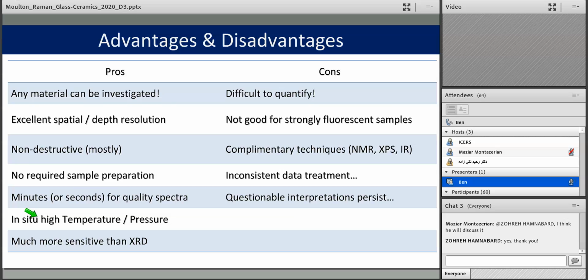And I just put another pro here that it's much more sensitive than X-ray diffraction. Any substitution, any distortion of the symmetry of the configuration of the elements will produce a change in the peaks. And so it's typically much more sensitive than XRD, and in fact, I would argue many other techniques. On the other hand, and we'll discuss this more in a moment, it's rather difficult to quantify.